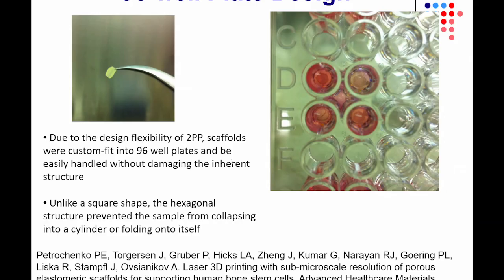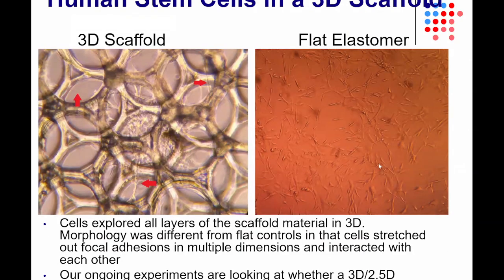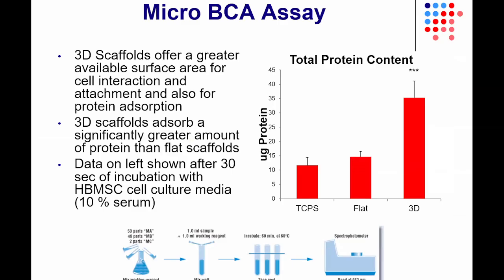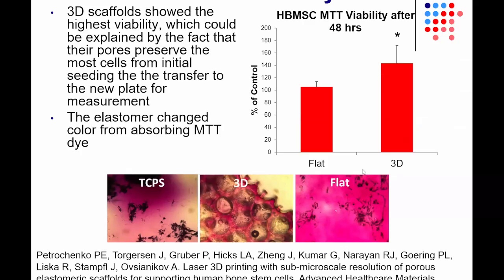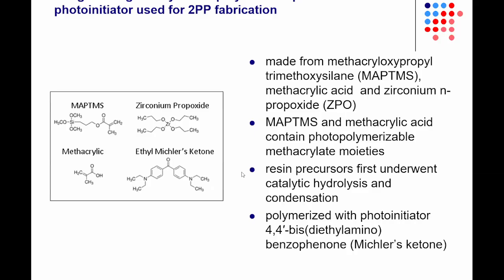You can see here a 3D printed structure placed in these wells. So these are all 3D printed structures placed in these 96 well plates. You can study the cell growth within these porous scaffolds. And certainly you can see stretched out structures with focal adhesions within these cylindrical structures. You can also see higher amounts of protein adhesion to the surface. So you can see here with the BCA assay, much higher amounts of protein adhesion to a 3D printed surface versus a flat surface or the tissue culture polystyrene surface. You can also see that you have higher cell viability rates. One of the things that you can notice is that the higher cell viability rate is probably related to the fact you just have a much larger number of cells spread over a 3D printed, 3-dimensional surface versus a flat surface.